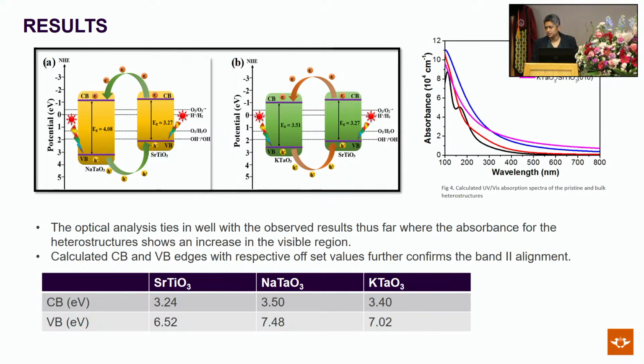Further information to confirm that this system is undergoing a band alignment was looking at the mechanism that was taking place and looking at the differences in values of the valence band and the conduction band. These values further confirmed that this new system is undergoing type 2 band alignment.